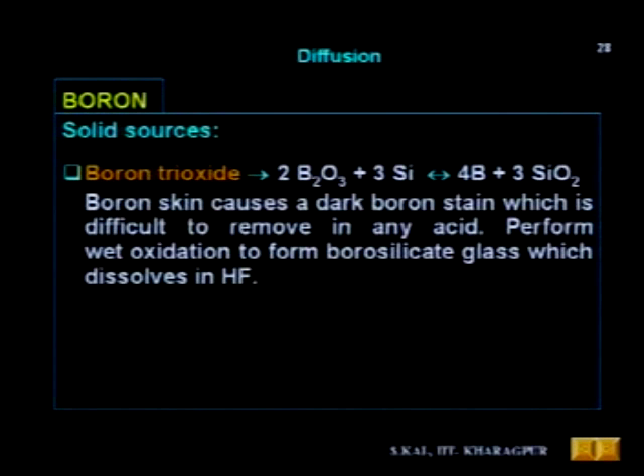So we remove that boron stain before driving diffusion, because this stain or boron skin forms during the pre-deposition diffusion, and it is removed by wet oxidation, which is normally done at very low temperature. That temperature is 700 to 750 degrees centigrade, and the time is about 30 minutes in wet oxygen. During that process, the boron stain or boron skin will form borosilicate glass, because along with boron, silicon dioxide is formed, and silicon dioxide and boron combined form borosilicate glass, and that glass can easily be removed in hydrofluoric acid, because hydrofluoric acid is an agent for glass, we know. So that is the advantage of forming borosilicate glass, so that the stain can easily be removed.